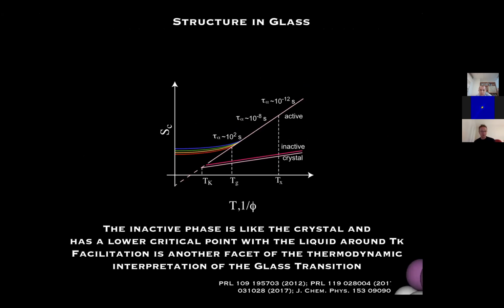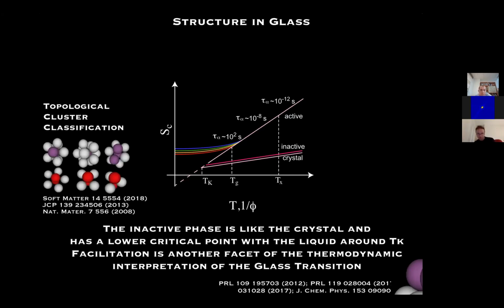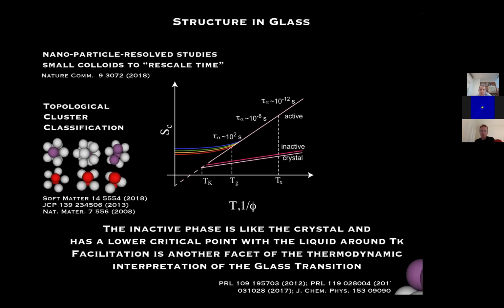So the central thing that I want to say is illustrated in this graph here, which is that we can now bring the dynamic facilitation story in line with the thermodynamic picture, and essentially we could argue that this is a resolution to the scientific revolution that is the glass transition. Okay, so other things that I mentioned that we've used along the way: the topological cluster classification, which is a means of identifying local structure in amorphous materials. And we've also developed this microscopy technique, nanoparticle resolved studies, which uses small colloids to effectively rescale time and thus enable us to get much closer to the glass transition than has previously been possible.